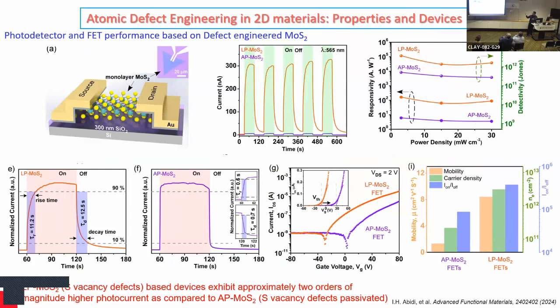For example, the low pressure CVD MoS2, which has sulfur vacancies in it, shows very high photocurrent as compared to the purple curve there. Once you have atmospheric pressure grown MoS2, which has oxygen passivation in it, the photo response is lower. But in terms of optoelectronic properties testing, we can see the response is fast in the case of oxygen passivated MoS2. But once you have sulfur vacancies, the decay is very long. So this decay can be useful in different device applications.